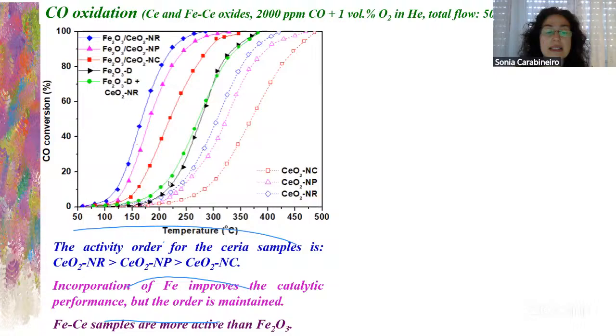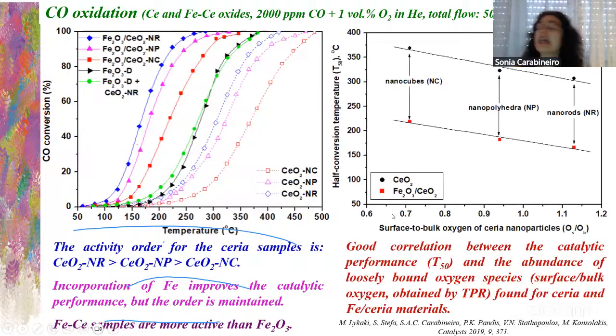So here we have a comparison of iron oxide prepared by decomposition of the precursor, and then added to cerium oxide nanorods, just a mixture to compare. And we see that the sample prepared by impregnation is much better here. It achieves a higher CO conversion at lower temperature. And we see that when we add iron, of course, they are more active than the iron oxide itself.